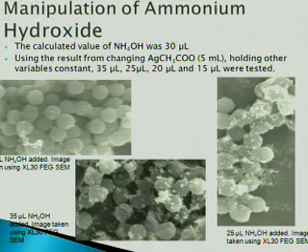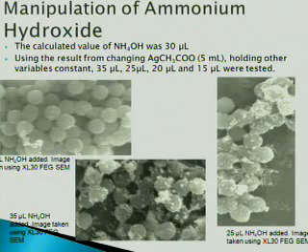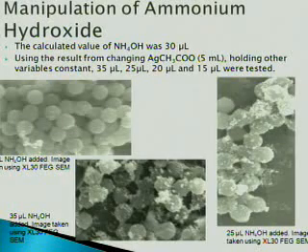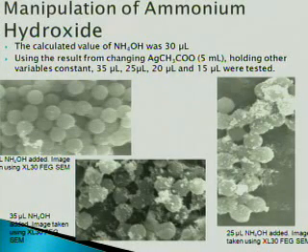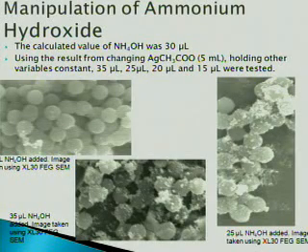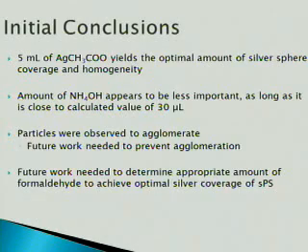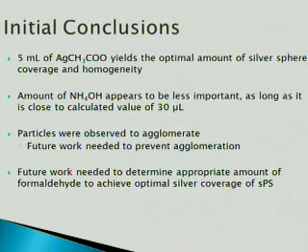We then decided to manipulate the amount of ammonium hydroxide and observe its effects. The calculated value was 30 microliters, so we varied a little above and below this. In conclusion, small variability didn't have much effect. But as we reduced the amount of ammonium hydroxide to 20 to 15 microliters, the reaction didn't really take place — probably because there wasn't enough ammonium hydroxide to react with the extraneous negative ions, preventing the reaction from proceeding. The initial conclusions were that 5 milliliters of silver acetate was the optimal amount, providing the optimal sphere coverage, and the amount of ammonium hydroxide appeared to be less important.